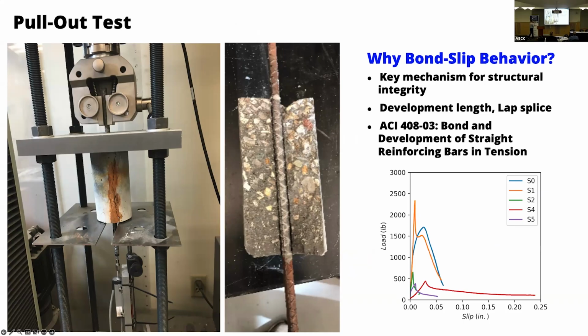If you see this graph over here, S0 means intact specimen, and S5 is the most corroded specimen. So you see that the profile is going to be significantly changing. Interesting thing is that if a little bit of corrosion is happening over here, like S1, then the bond slip response is sometimes even better than the intact one. So it's not always happening. However, we often observe that kind of pattern as well.